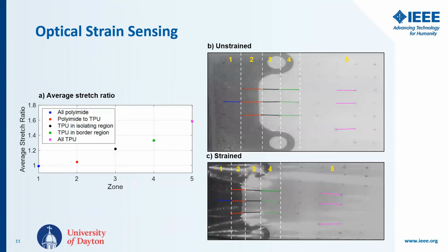So in order to more accurately figure out what was going on in our boundary, we did optical strain sensing. We took a pattern of ink dots and placed them on top of our sample, and then used an optical method to track the dots as they were strained under tension, and set up several different areas in our sample. So we tracked the movement on the polyimide, on an area that was between polyimide and TPU, an area that was only in the TPU isolating region, an area that we called the border region, and then our unconstrained TPU sample. So plotting those on a graph, we have a gradient of stretch, essentially, from left to right on the sample, which allows us to keep our traces from disconnecting under high strain.